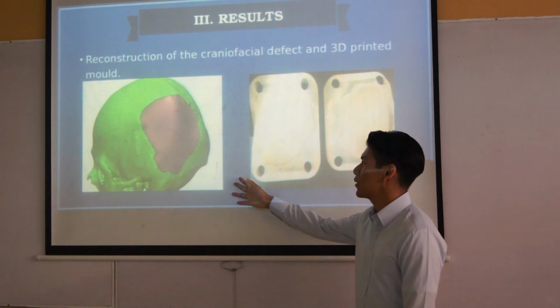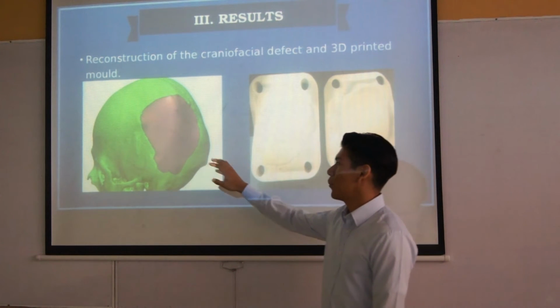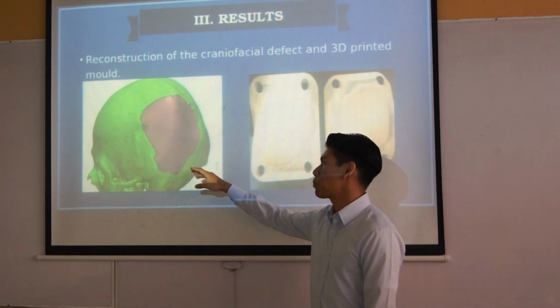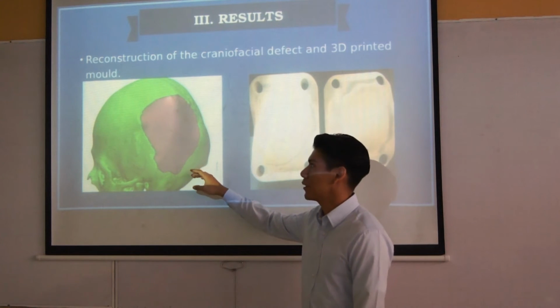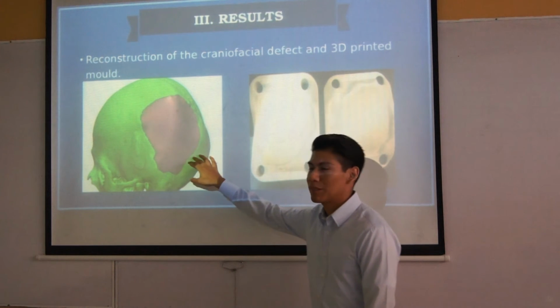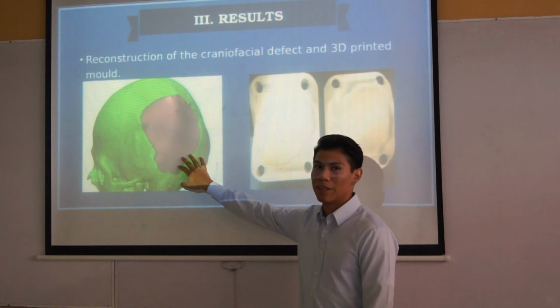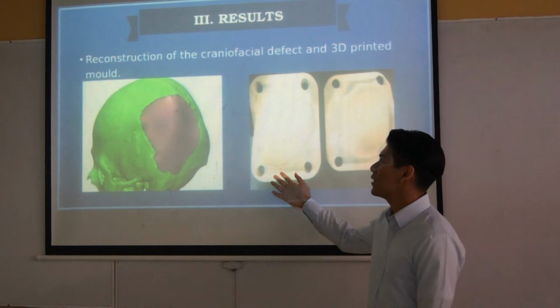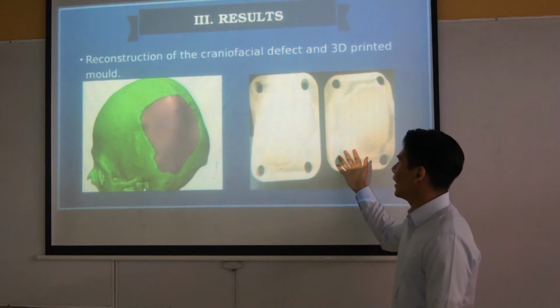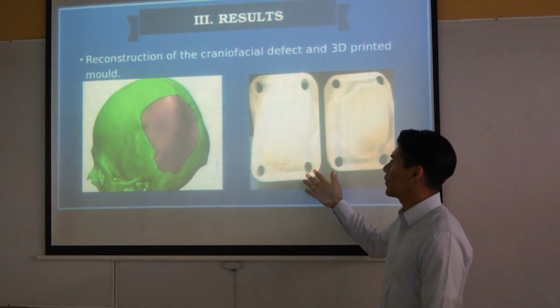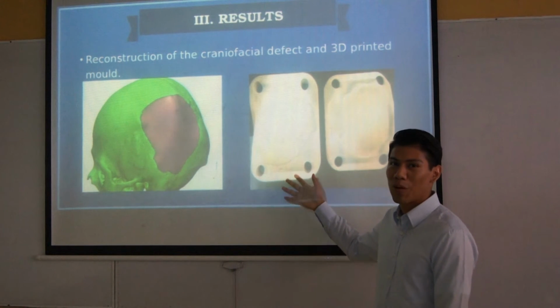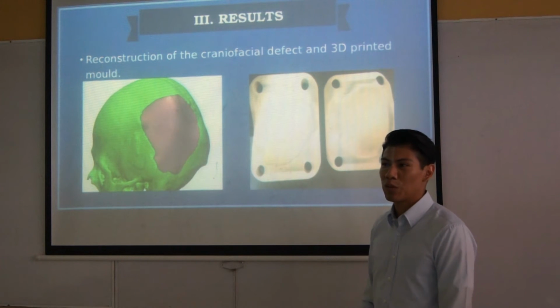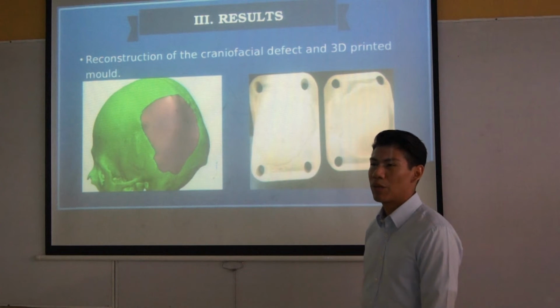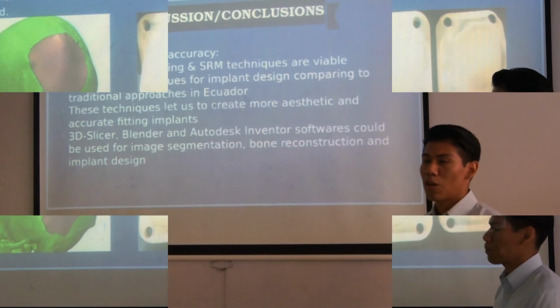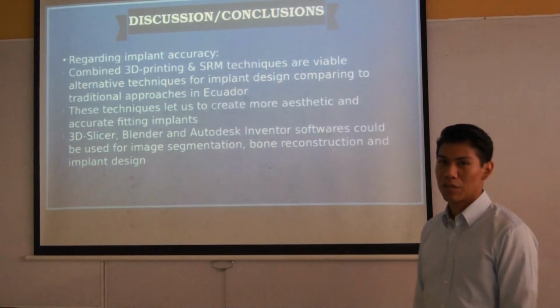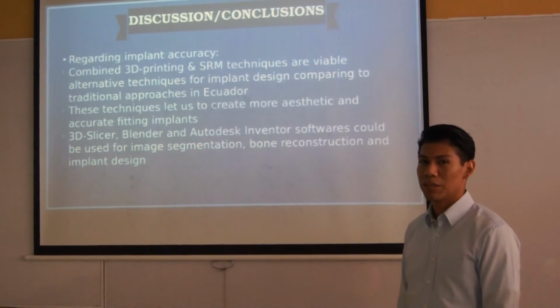This picture shows the reconstruction that we did on Blender and with the segmentation in 3D Slicer. Here is the corrected defect using the model we created in Blender. After this, we designed a mold in a 3D printed mold. This mold was used to create a model that we then used to create another mold made of silicone rubber. Okay. Now for the discussion and conclusions regarding implant accuracy.